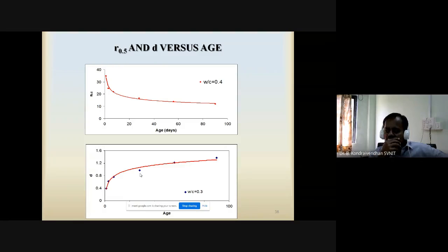Why is it happening? Because of the progress of hydration over a period of time, refinement is happening. More and more CSH gel is forming. That's why the pore size reduces, and after some time it becomes asymptotic to the x-axis. That's how the R0.5 versus age curve will behave.